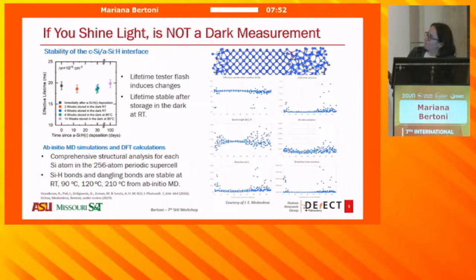And what you see on the right-hand side is some molecular dynamics calculations that have shown that really in the dark, you shouldn't have a whole lot of problems and a whole lot of changes, just a pretty stable interface, as long as it's an amorphous silicon interface.